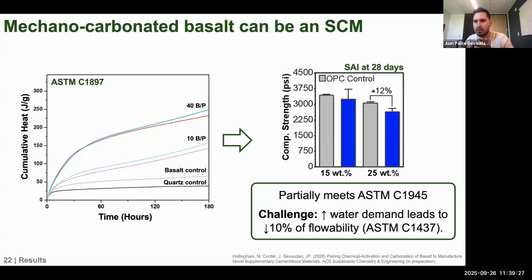Now, of course, translating that to the strength activity index at 28 days, we see that at 25 weight percent, we actually decrease the compressive strength by 12%. And the reason why that is happening is because we have a challenge here. We're increasing the water demand in our basalt SCMs, which then decreases the flowability of our mixtures. So the water demand right now is the biggest issue that we need to overcome in these manufactured SCMs for them to be applicable and used in the field. We're actively working on that, and hopefully I'll be able to share some other papers on that soon, and our advances on that.